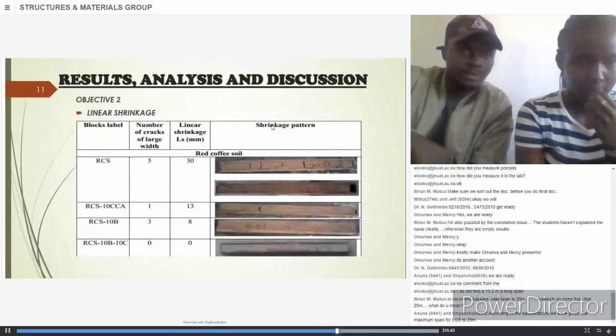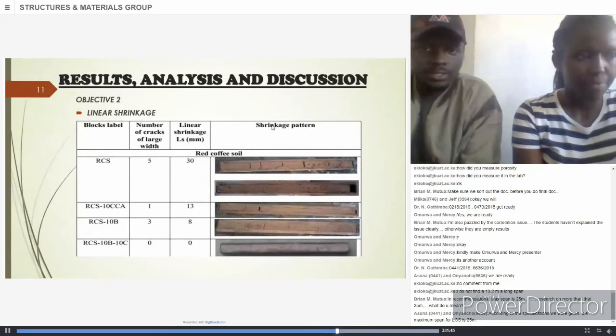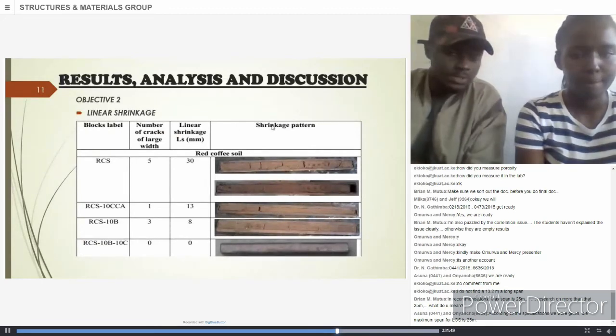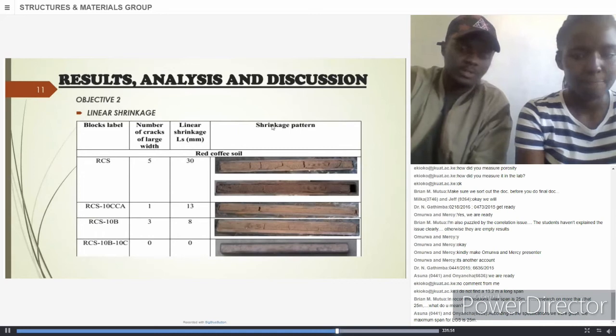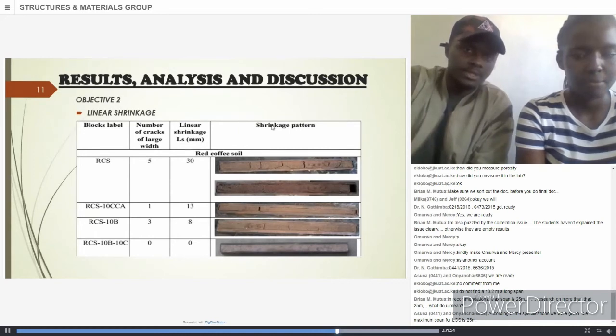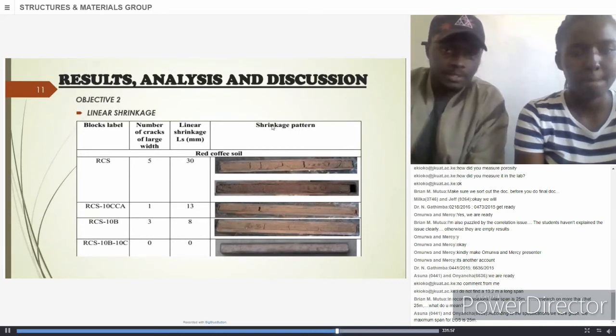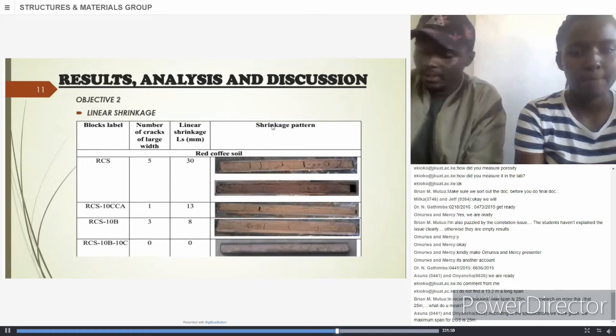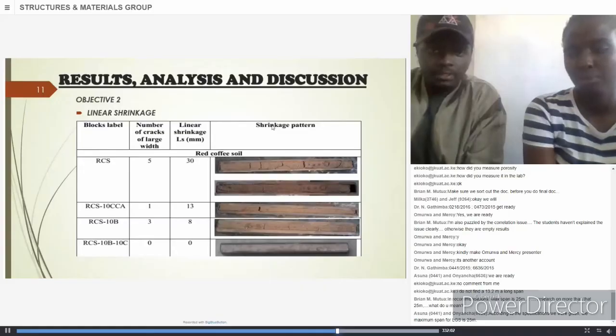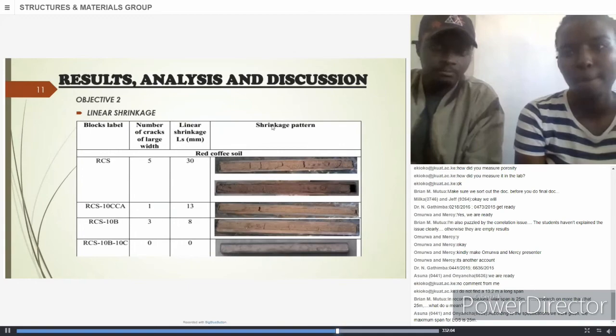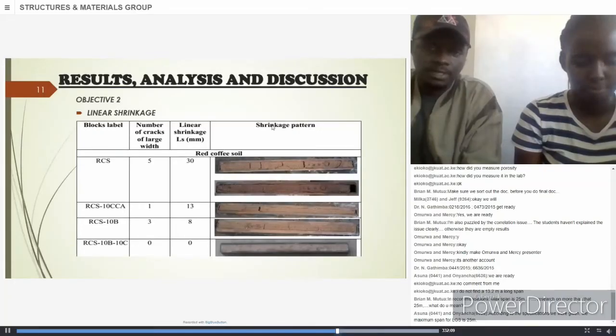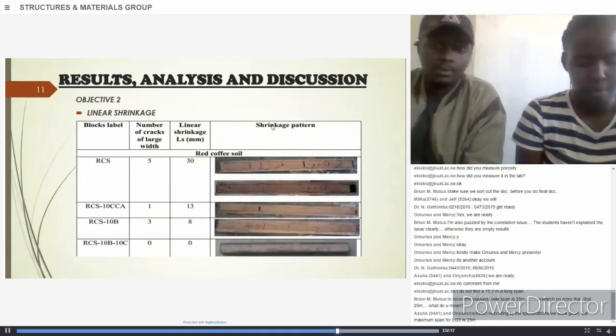So on objective number 2, we move to the linear shrinkage, whereby we selected blocks which we had made from the compositions I showed you earlier. And as you can see, the number of cracks and the linear shrinkage, and I can comment on that, whereby as we added the corn ash and bagasse, the number of cracks reduced as well as the linear shrinkage. Else we observed that there was no crack on addition of cement.